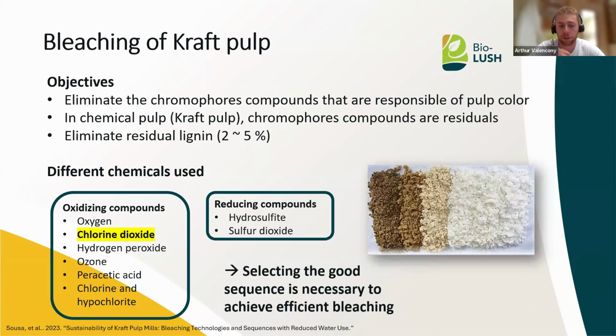Different kinds of bleaching can be found today with different compounds, the oxidizing ones and the reducing ones. The one which is the most used is chlorine dioxide, but it contains chlorine, so it can be hazardous for the environment. This is why some totally chlorine-free chemicals are used, such as hydrogen peroxide, ozone or oxygen, to bleach the pulp and eliminate the lignin and the brown color that we know of the kraft pulp.